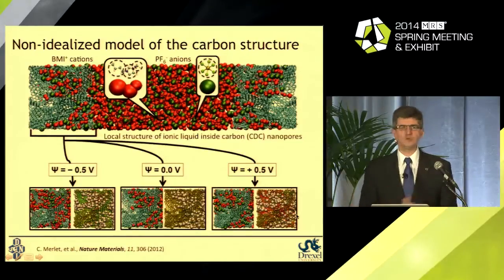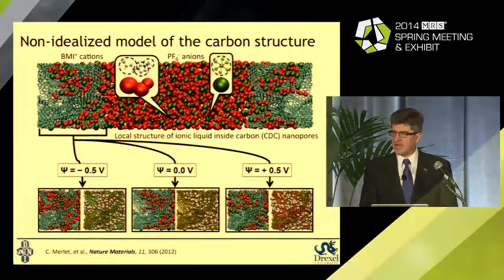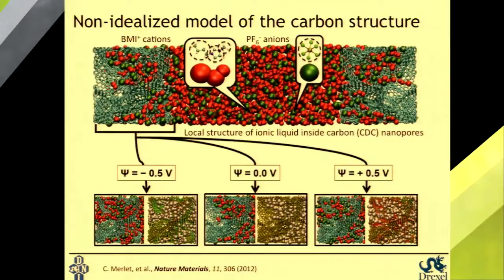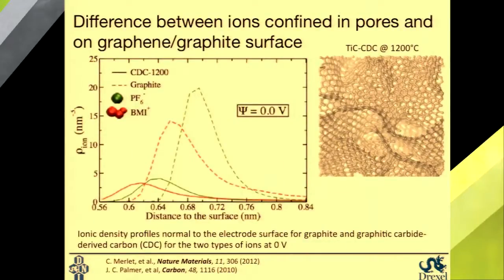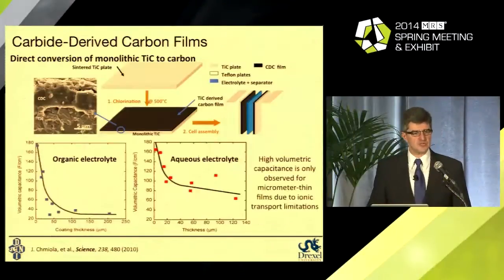So basically what is happening, slowly, step by step, from a very empirical field where people were developing devices by using activated carbons and trying to match them to electrolytes here, we get more and more understanding of what is really going on with ion confinement, how they behave, transport characteristics, performance, storage here. So we come to the stage when we can develop materials that really match our requirements for performance. And you will also see by using the same MD simulations that, for example, planar graphite and a three-dimensional network, even close to graphitic structure, will have different characteristics. Ions will be located at different distances from the surface of the material. So really, different materials behave differently here.